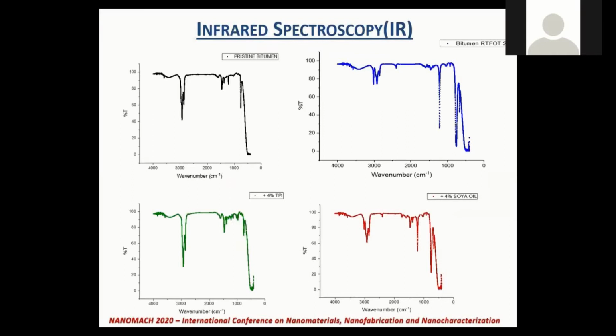The first thing to observe is that the black spectra relating to non-aged bitumen almost overlap with those obtained for aged bitumen plus 4% TPI, as well as those obtained for aged bitumen are very similar to those obtained with aged bitumen plus 4% soy oil. Analyzing in depth, we observe how the peak relative to the stretching of aromatic compounds in aged bitumen is drastically reduced. In the sample with the TPI additive, this peak grows until it reaches values similar to the initial pristine bitumen, which does not happen in the sample containing soy oil.